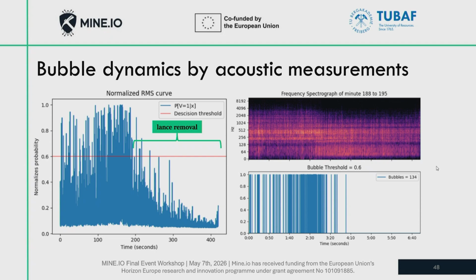Here you can see also the lance removal. It suddenly reduces the bubble intensity because there's no bubbling anymore. So you can also see here if something's happening which is not planned, or you can verify that, for example, the lance position is probably driven.